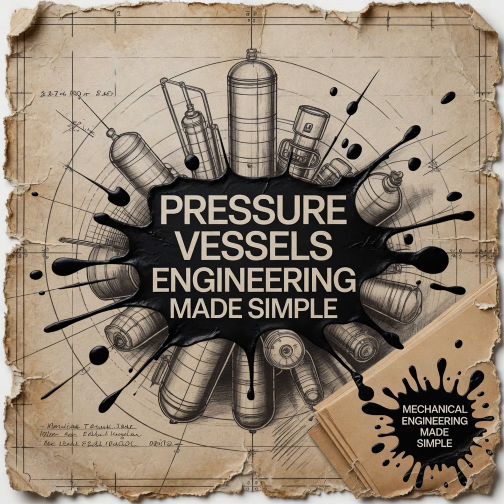So they take this test plate and they subject it to a transverse bend test. They force the welded sample into a tight U-shape around a steel former. The bend test is ruthless. I bet. The outer fibers of the bend are subjected to massive tensile strain. The inspectors are closely examining the surface of the HAZ during the bend. What are they looking for? They're looking for any tearing, crazing, or microscopic fractures. If the HAZ has become too hard and brittle due to improper heat input, it won't stretch around the former. It'll just snap. It will simply snap.